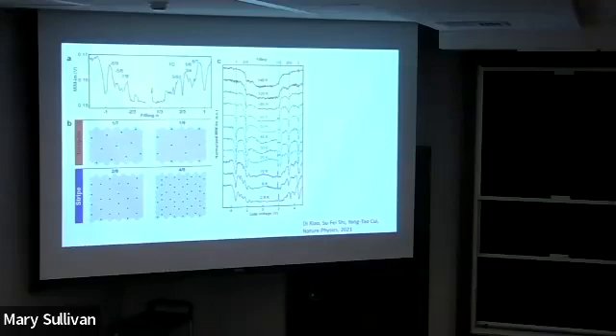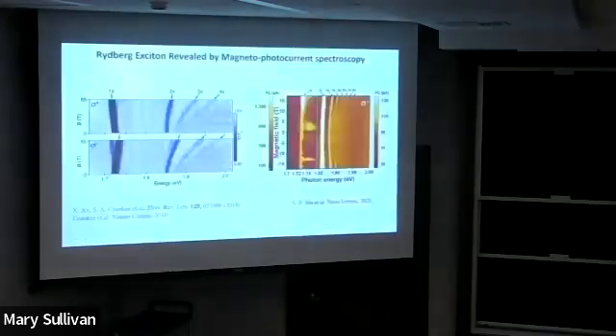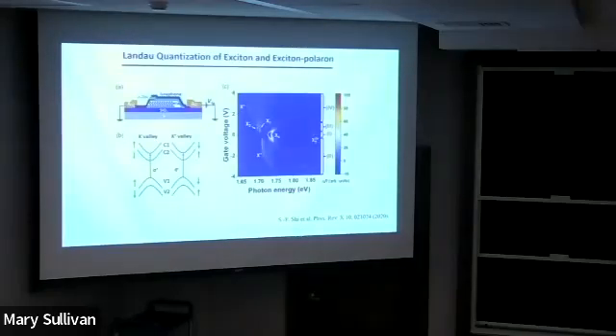Yes, we do have the reflection measurement. I actually have this measurement here. This is a reflection spectrum. For a monolayer, you can sort of approximate it as absorption. So the exciton absorption is here. That's actually 2s. Is it shifted from what you're seeing in your PL? No, it's actually roughly the same. Again, if you check a different spot, it's going to be different from sample to sample. But if you look at exactly the same spot on the same sample, it's roughly the same.